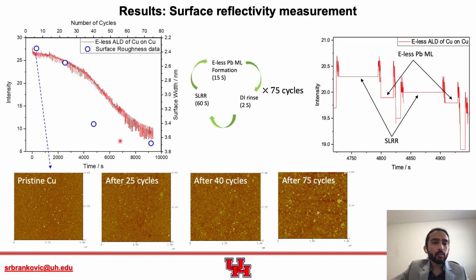So overall, the trend we can observe is that as we deposit copper on top of copper, surface becomes more rough. So there is increase in surface roughness, and at the same time, there is a decrease in surface reflectivity. And this graph here shows a zoom in version of any of these 75 cycles. And we can notice here that the setup is able to distinguish between the reflectivity changes after SLRR cycles or after lead monolayer formation. And this gives us an idea about sensitivity of the setup as well.